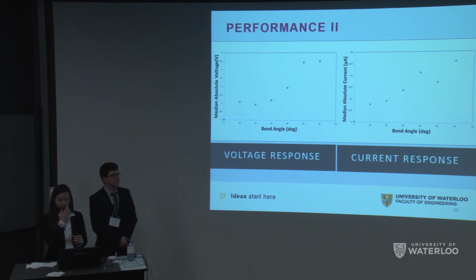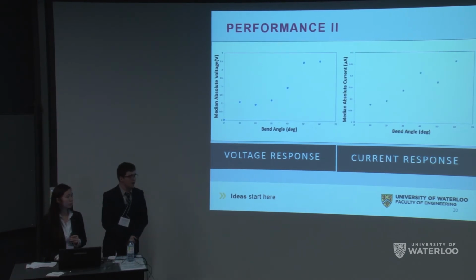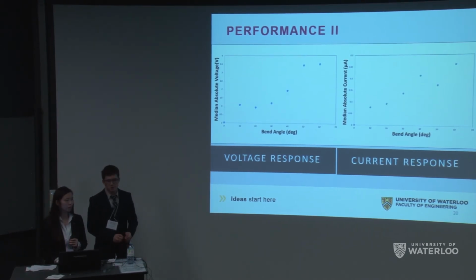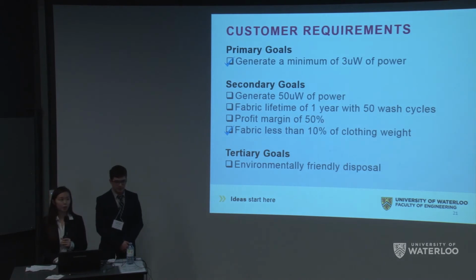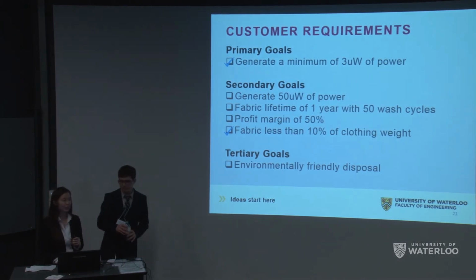It's important to note that the max bending didn't display an exactly direct characteristic. Instead, it had a bit of exponential factor to it. And we believe that not only are we deforming the film more at this high angle, but a larger area of the film is deforming, which gives us that signal. So now it's important to go back to our customer requirements to see what we actually achieved.